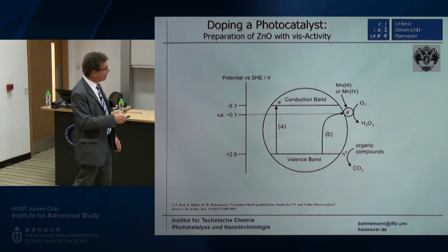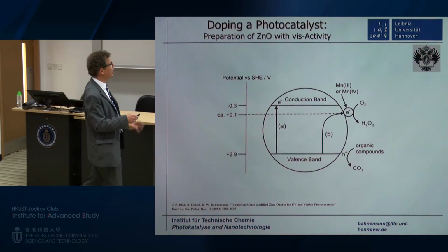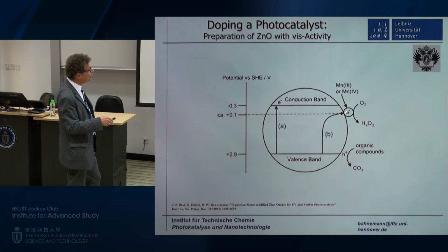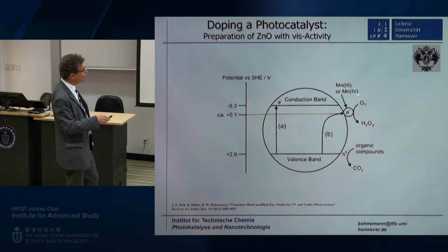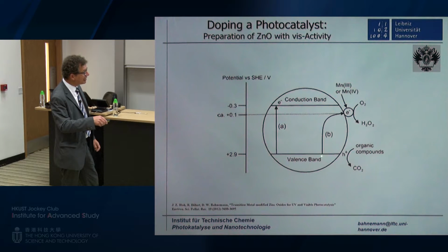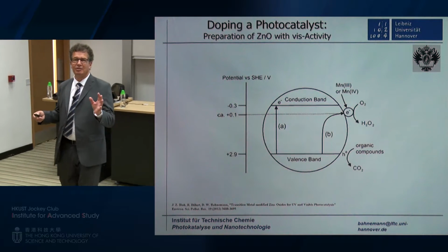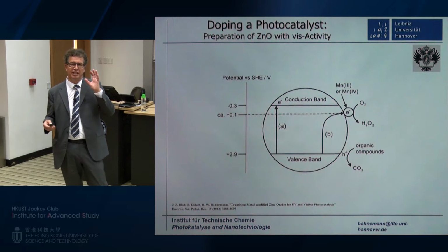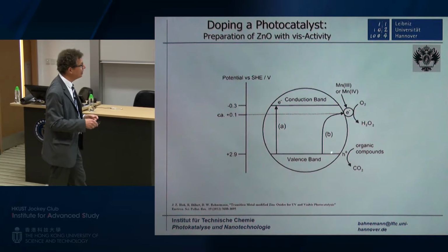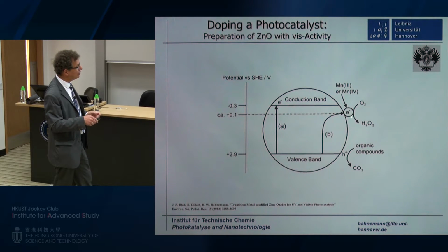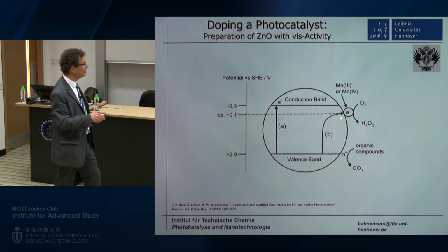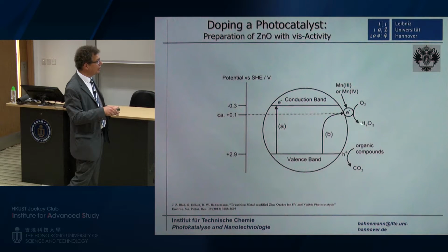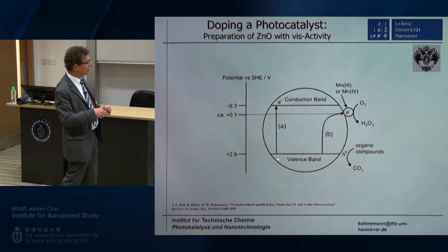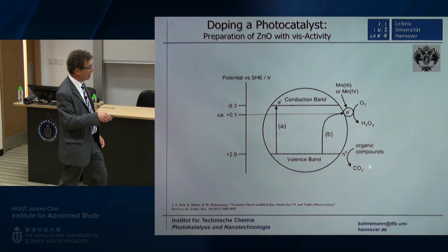What do we think is happening here? We think if we have a lot of manganese, it's not only incorporated in the zinc oxide, but it forms islands on the surface. And these islands probably contain manganese 3 or manganese 4. And these islands can be excited directly. An electron from the valence band can now be excited by visible light photons directly to these deposits on the surface. This is something found with TiO2 for so-called grafted TiO2. Hashimoto, for example, and his group has done a lot of work on this, and we find a similar effect here for manganese on zinc oxide, probably as a manganese oxide on the surface. And if the electron goes there, then the reduction reaction will occur here, while the oxidation reaction still is using the holes in the valence band to oxidize our organic compounds, our acetaldehyde, to carbon dioxide.